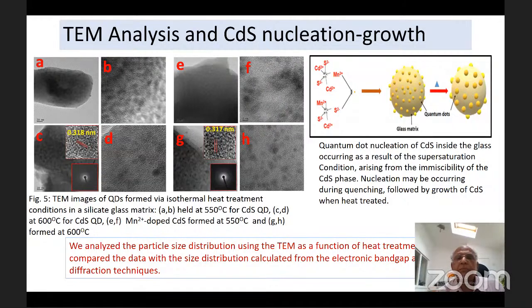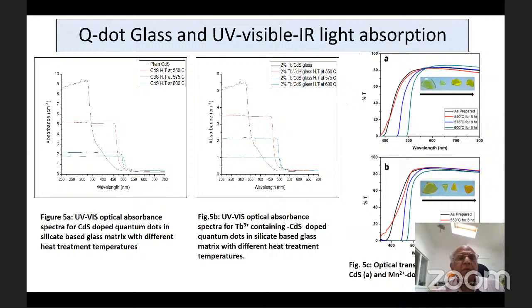In this slide, we see how the UV visible spectra of CdS containing and terbium doped CdS containing quantum dot glass are changing, and it's becoming very large, particularly in terbium doped CdS glass, which contains 2% of terbium oxide. We can also see how the band gap is shifting in the transmission spectrum.